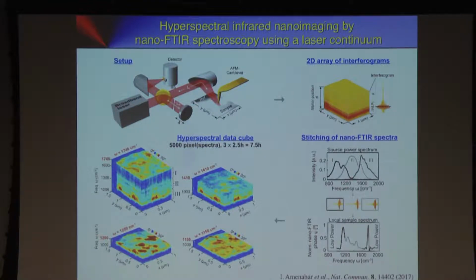In the meantime, laser technology has evolved, and also the electronics and hardware of the NeaSNOM improved. And now we can record actually spectra with a medium resolution in about 100 milliseconds, and it's possible to get such a cube in 20 to 30 minutes. So we are coming closer to the goal of doing regularly hyperspectral imaging. Also, there's a little bit of way to go.